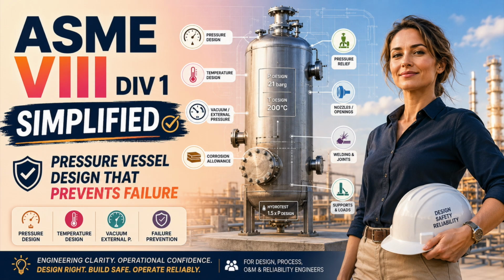A corrosion allowance can compensate for expected general metal loss. It cannot reliably protect against every degradation mechanism. Pitting, stress corrosion cracking, hydrogen damage, erosion, crevice corrosion, and corrosion under insulation do not behave like uniform thinning. Adding thickness may provide little protection against a cracking mechanism.